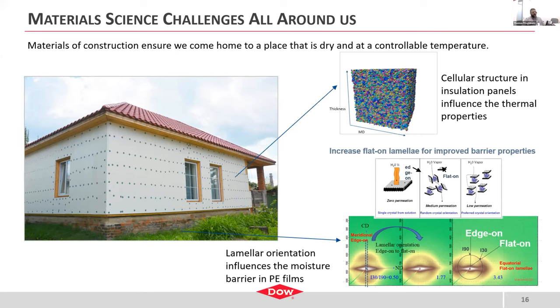Secondly, there's often a chemical blowing agent that is used that resides inside the cells of the foam, which has a lower thermal conductivity than air, and therefore reduces the thermal conductivity of the panel further. Third, and the way that we at Dow really try to impact the thermal insulation market is through the control of the cellular structure.